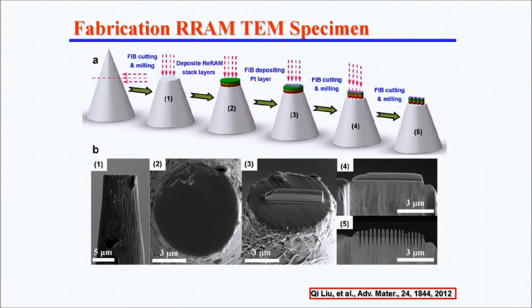Then we try to understand the dynamic process of this filament forming. This is a very challenging job because in-situ observation of a vertical device is very challenging. So how to make a sample is very important. We tried a lot of different methods. Finally, we chose the TEM tip. We fabricate a whole device on these TEM tips. This is the detailed process. Finally, we can make a series of devices on one tip. That means we can provide enough samples for the in-situ TEM observation.